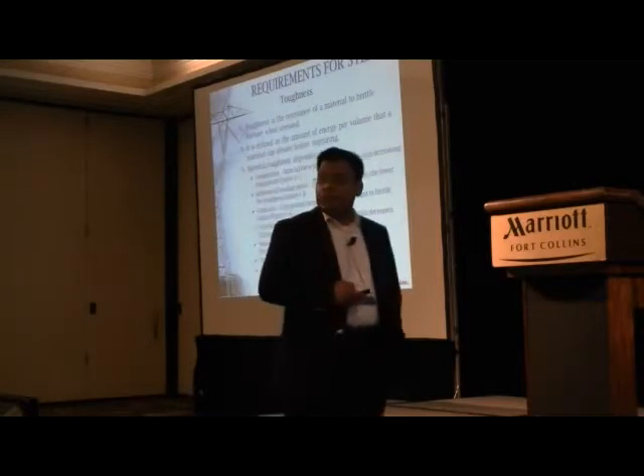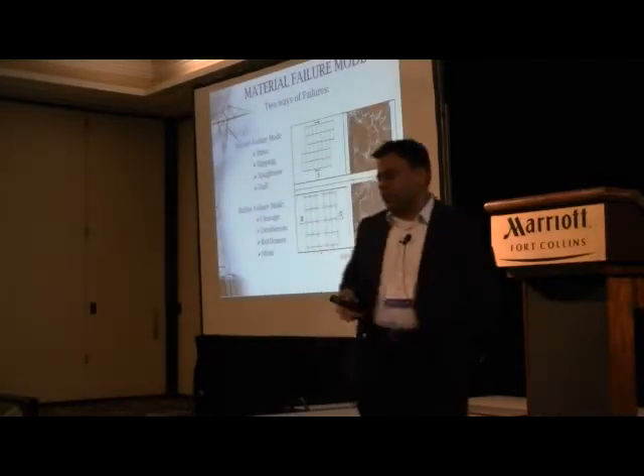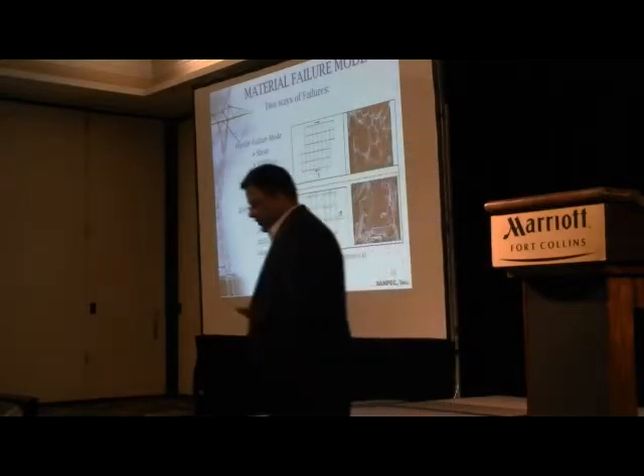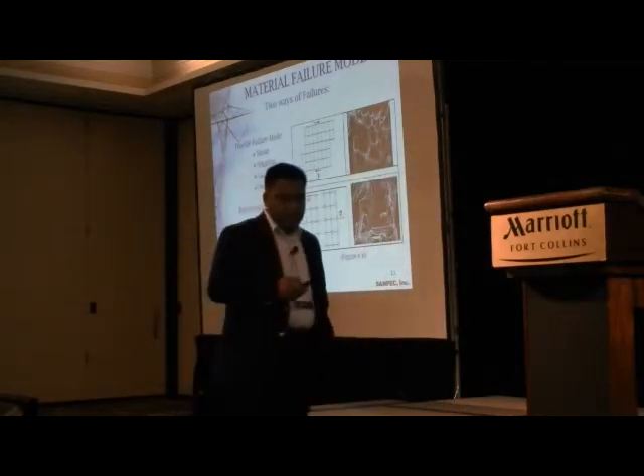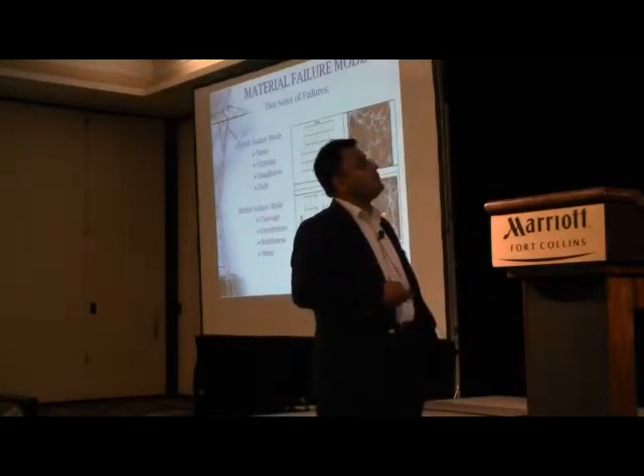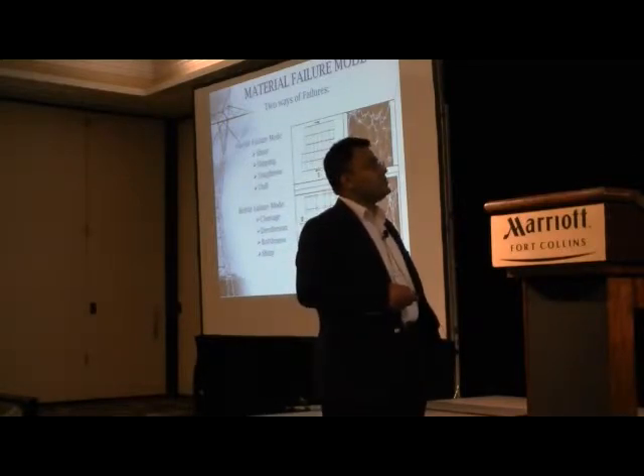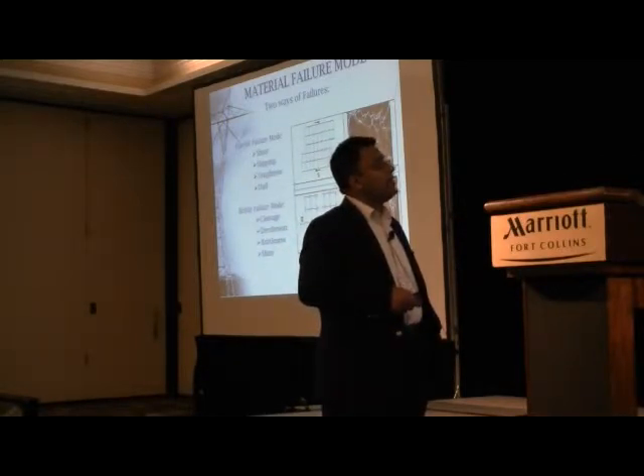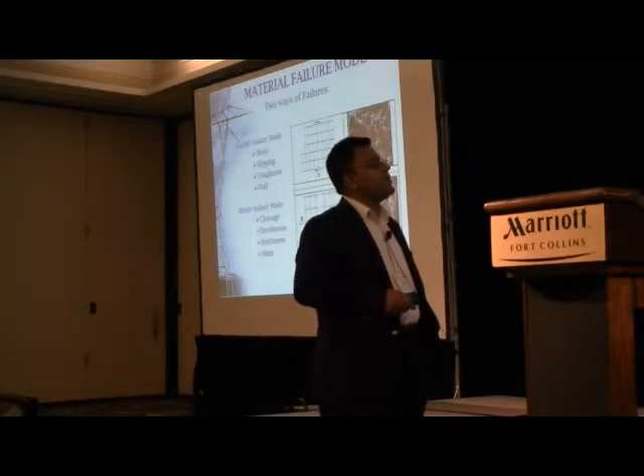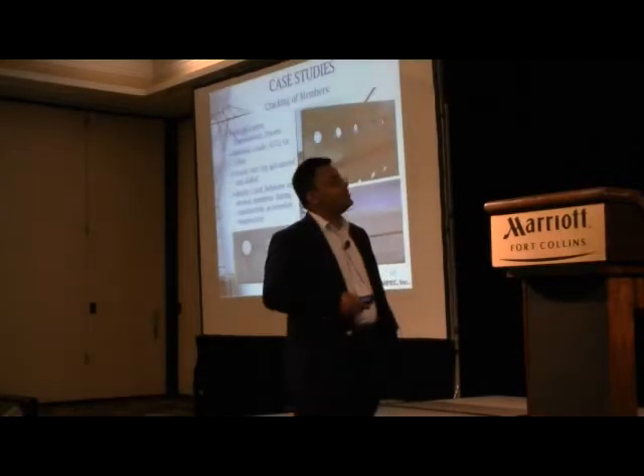So toughness is very critical. We talked about that. Now, in the normal type of failure that you have when you lack toughness, one of the normal general failures that you would notice is the brittle failure. Of course, with ductile steel, you have more ductile failure, which you all know: shear, slipping, and a dull kind of finish that you'll see. But most of the time, with lack of toughness, you'll see brittle failure, which is cleavage, decohesion, brittleness, and shining. That's what you will see.